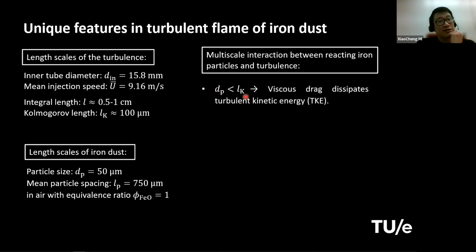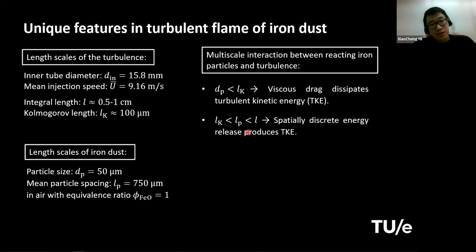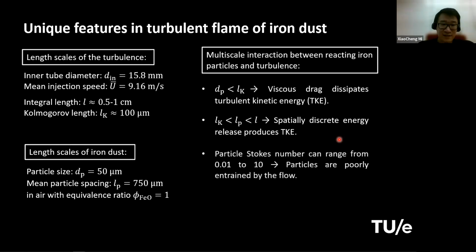The first one is the particle size is actually smaller than the Kolmogorov length scale of the turbulence. So viscous drag on these particles tends to dissipate the turbulent kinetic energy. That's number one. Number two is this particle spacing is actually between your Kolmogorov length scale and the integral length scale of the turbulence. So this is interesting. That means your particle itself tends to dissipate the TKE, but the discrete energy released from these particles tends to enhance or to produce more turbulence kinetic energy, because the spacing between the particles is in this intermediate or energy producing length scale range.